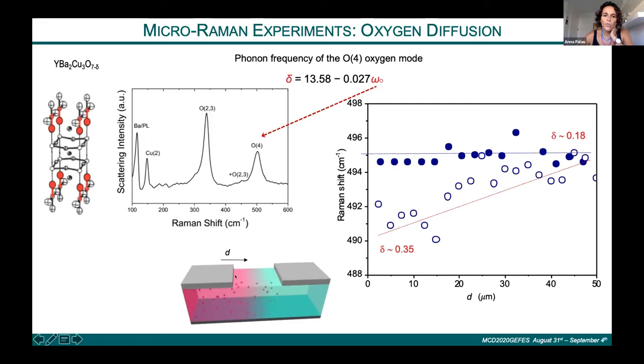This kind of experiment can be very useful to evaluate, in a continuous way, different properties of the material in different doping states. For example, here we have a free material without any electrode on top, which has this gradient of oxygen. We applied the pulse between this contact and this contact, inducing a gradient of oxygen between one contact and the other. We measured with micro-Raman the delta values of the YBCO at different positions between one contact and the other. By measuring the vibration of the oxygen 4 in the Raman mode, we can use this experimental equation to determine the delta. We start from a system, the black full points, which is optimally doped, and we produce this gradient of doping by doing this pulse. And this is completely reversible.